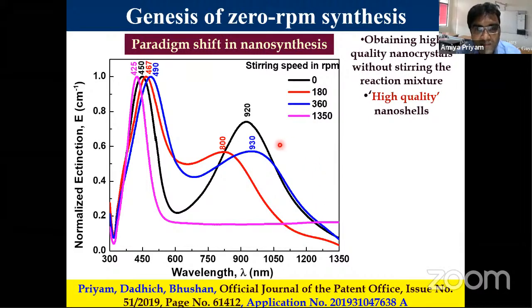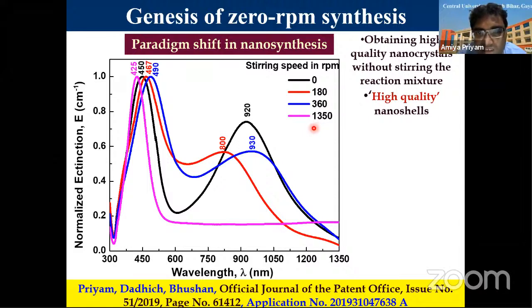We carefully analyzed this system and found, as you can see here, different stirring speeds: 0, 180, 360, 1350. We found that as we reduce the stirring speed and finally go to 0, we get a very nice peak in the near IR region, which was desired for biomedical application. 920. So this is the kind of nanocrystal that we need, which has a small FWHM and a red-shifted peak towards the NIR. So we are clearly in the first NIR window now.